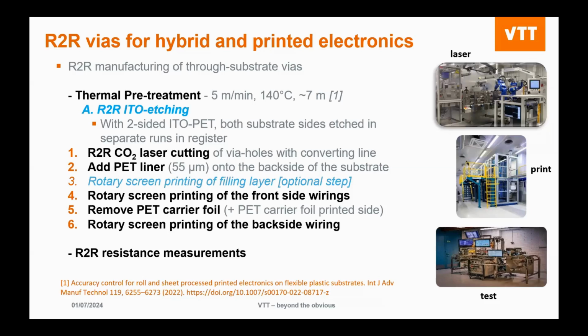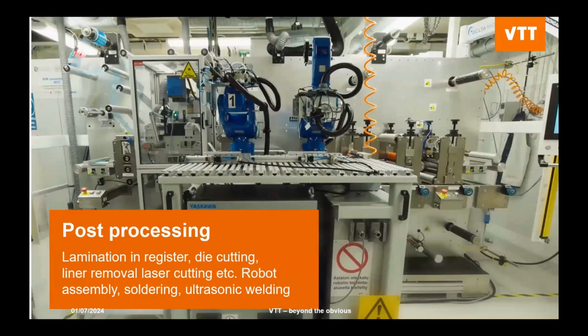That's something we proved in this paper that I published recently in the International Journal of Advanced Manufacturing. So after that's done, if you have, of course, ITO on your substrate, you'll want to do ITO etching. We do wet etching at VTT. And then when we want to do these vias for the double-sided systems, we use our roll-to-roll CO2 laser line. And then we also add a PET liner. This is done on this converting line up in Oulu.